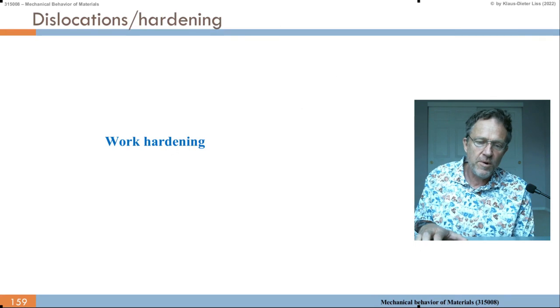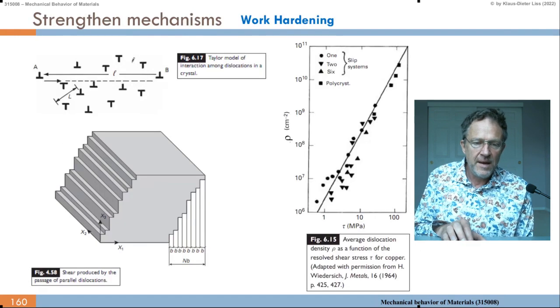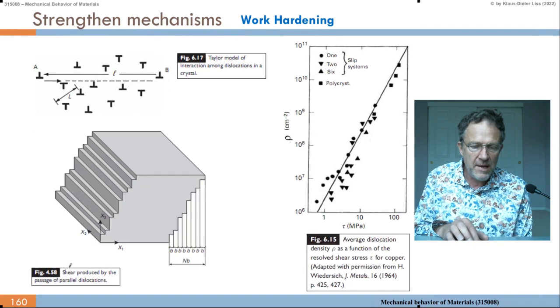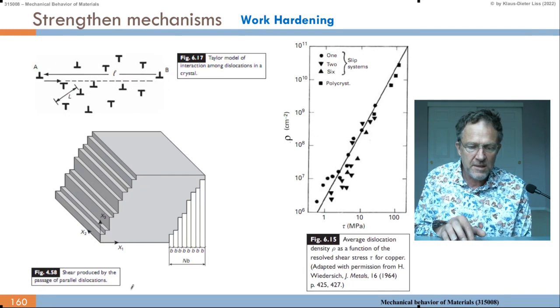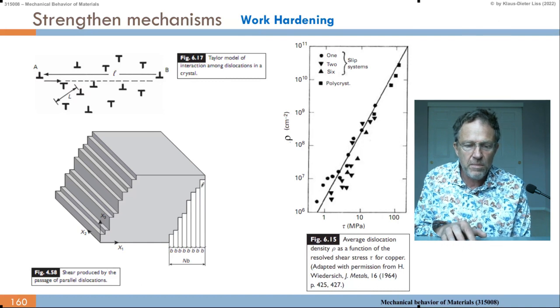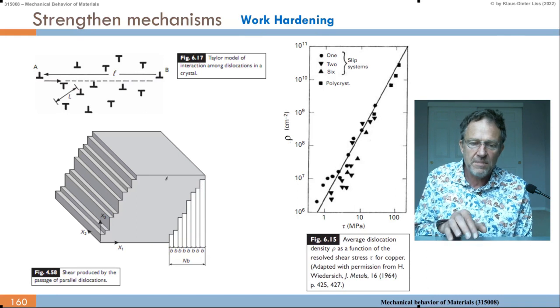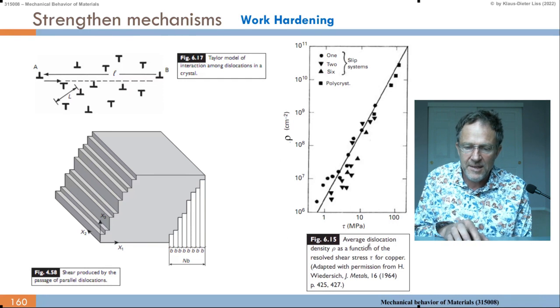So let's look more into work hardening. If you have many dislocations, we can make this model here. The shear produced by the passage of many parallel dislocations, then we get steps at the surfaces, which are each time 1 Burgers vector. And we have many of those steps. Of course, sometimes we can have 2. We call that the Taylor model of interactions among dislocations. And that gives us the following plot, namely we have here the shear stress in megapascal and the dislocation density per square centimeter, and see this linear behavior.